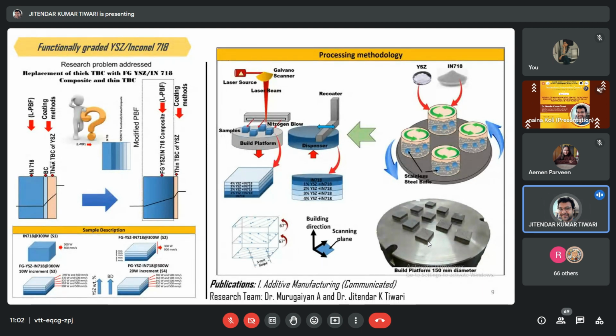Most metals will either melt at that temperature, or get softened, or lose their strength. We also need ductility, because it also needs load sustainability. So for that, we perform some coating on the metal. For example, Inconel 718 is a type of nickel based superalloy with around 1400 degrees centigrade melting temperature. If you are going to operate it at 1600 degrees centigrade, obviously it will melt. So we need to perform some coating. That coating is a kind of ceramic, yttria stabilized zirconia.